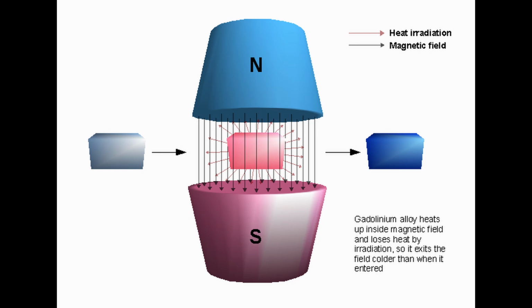What kind of materials are actually good candidates for this magnetic refrigeration thing, especially if we're talking about everyday things like refrigerators? You've hit on a very important point. So this magnetocaloric effect, it's something that all magnetic solids have. But the effect is strongest near the material's magnetic ordering temperature. This is the temperature where the material switches between different magnetic phases. Now, for something like a fridge, you'd ideally want this temperature to be near room temperature, right? That makes sense. Another key factor is how much the magnetic order in the material changes during this transition. A big change means a bigger temperature difference, which is what we want.